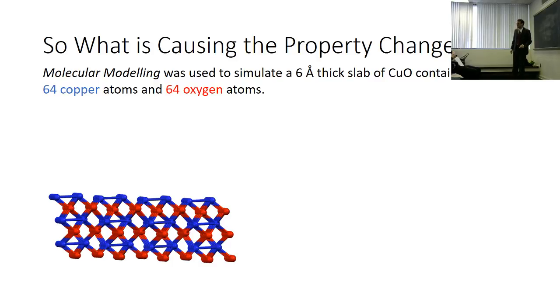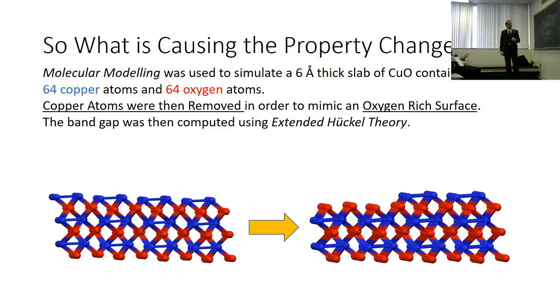I did what any good experimentalist does: I talked to computationalists. Collaborators in the Batista group, Dr. Batista up on Science Hill, were kind enough to model a copper oxide nanosheet in their computer. Then what we did is we removed some copper atoms from the surface and used their theories, their programs, to measure the band gap of this theoretical material.